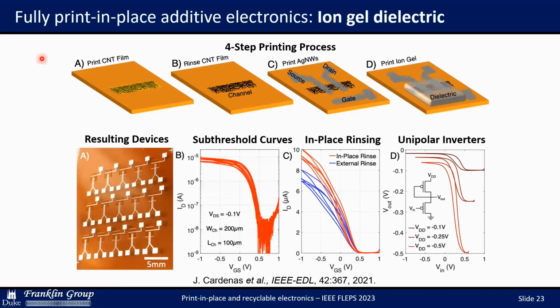So an advantage of an ion gel is, of course, it drives down the needed voltage for switching the transistor. It's only a 2-volt swing for a full modulation here. The downside is that any ionic dielectric is going to have limitations in terms of switching rate or sweep rate, because you're relying on ionic motion, which is inherently slower.